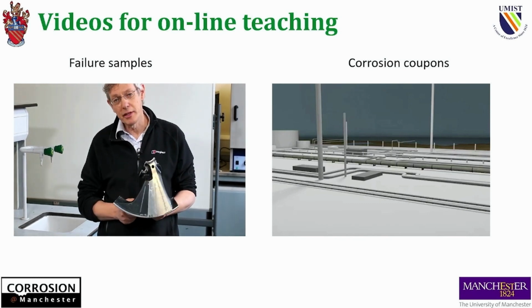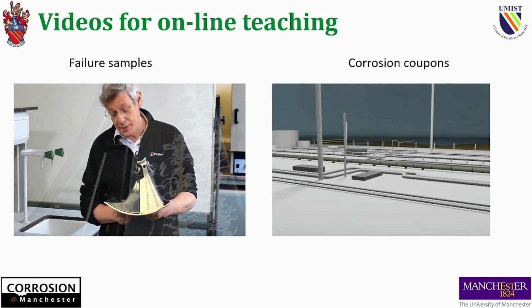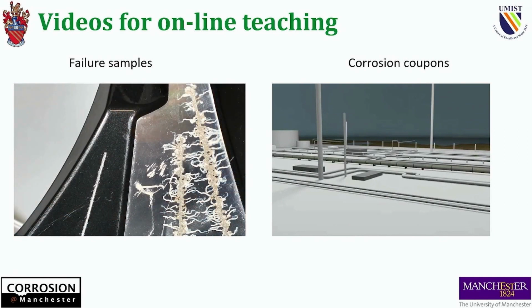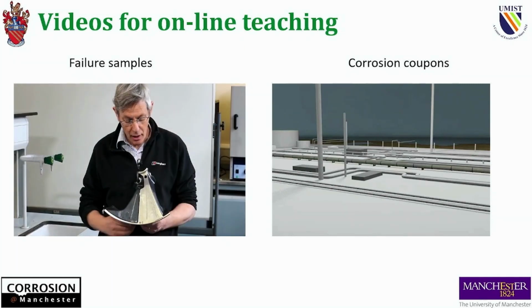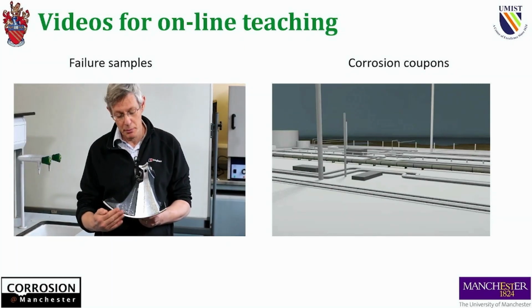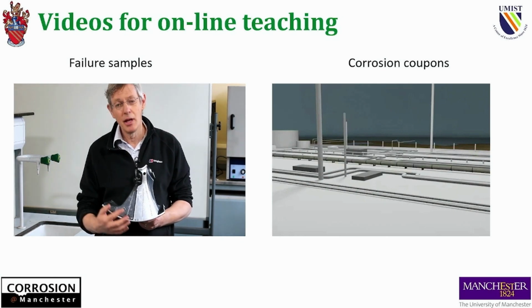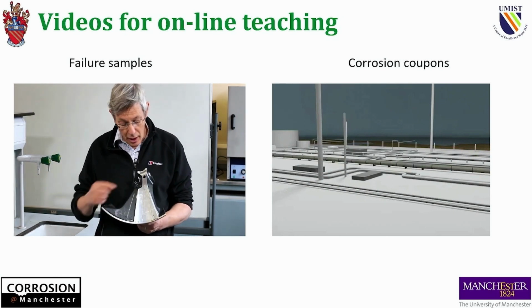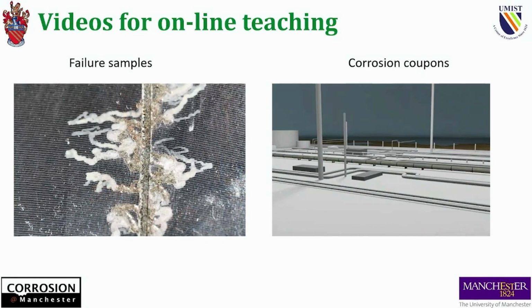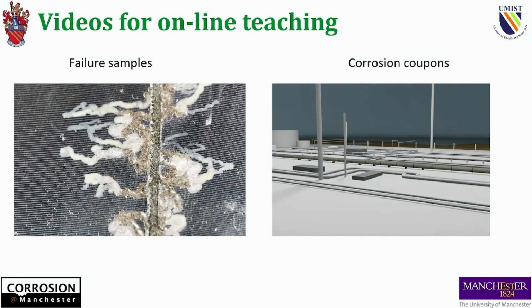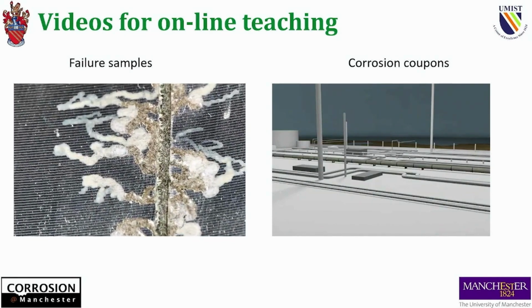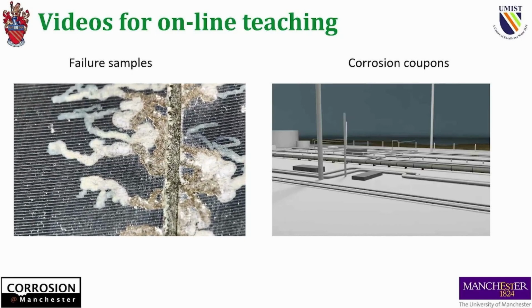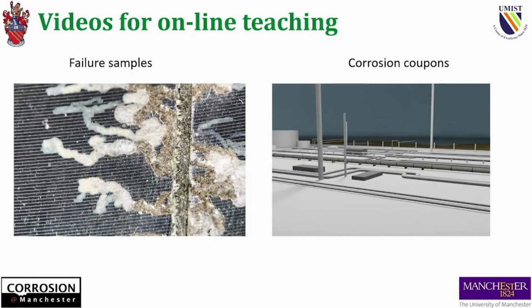Now the alloy wheel is made of aluminium alloy, and it's painted. It might not look as though it's painted, but these dark colours are from the powder coating that's put on the wheel for corrosion protection. When you bump your wheel against the curb, it damages the paint system and the wheel starts corroding. And we've shown this here by damaging the paint coating artificially and exposing it to the atmosphere, and we get this very pretty corrosion which we call filiform corrosion.